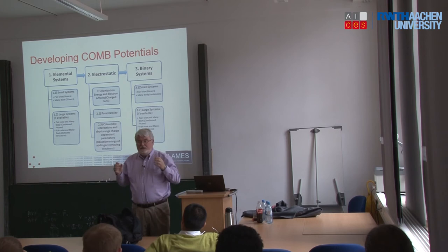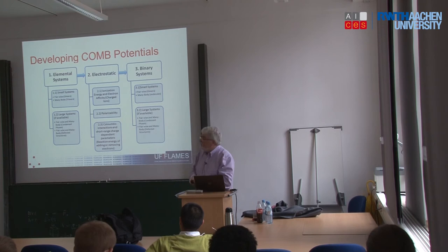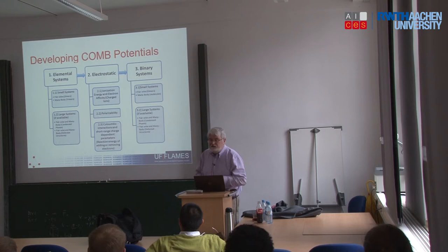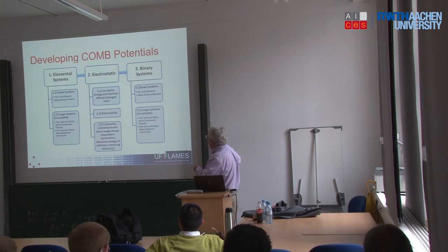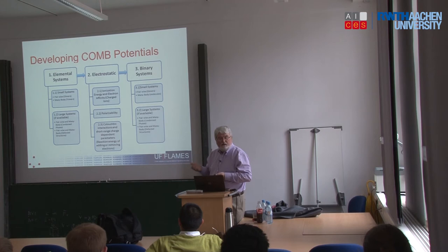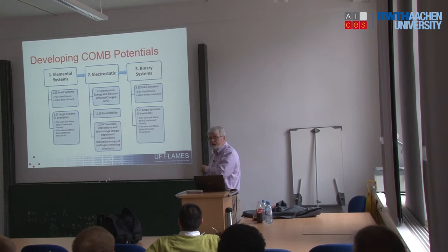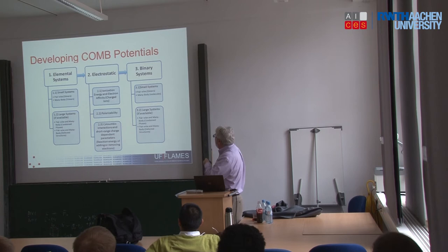Then we look at trimers. Then we build up to larger systems, solid-state systems. If you go through this process, then you can actually determine reasonable values for a number of parameters for that one element. And you go through for each of those elements and get some parameters that way. So first of all, we start off with the individual elements. Then, of course, you have to start looking at electrostatic interactions. You want to get the ionization energies correct. What's the cost of ionizing nitrogen or the cost of ionizing aluminum? We can do those calculations with DFT or Gaussian or something like that, or there are experimental values in many cases. We can build those in. So that gives us some of the energy cost. So we've got pair interactions plus the cost of the electrostatics of charging and uncharging things. We need to capture some of the physics. Then we add those together and look at some simple binary systems, like a pairwise system: aluminum and nitrogen together.